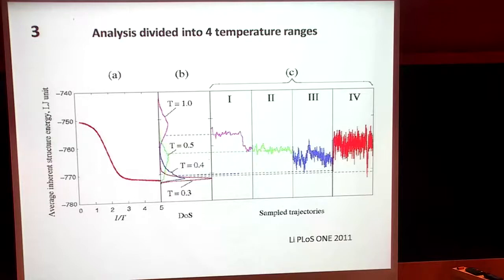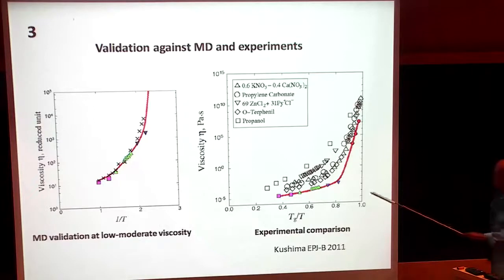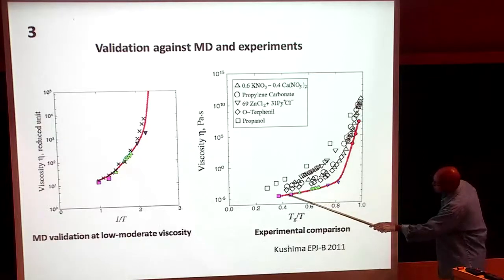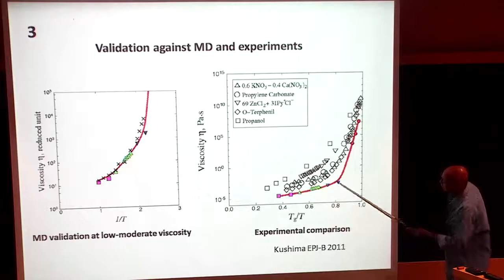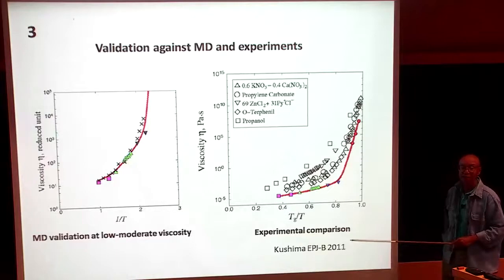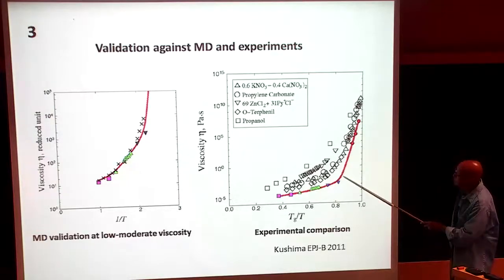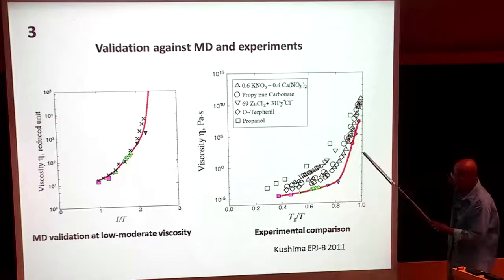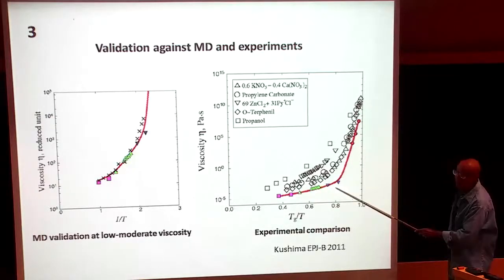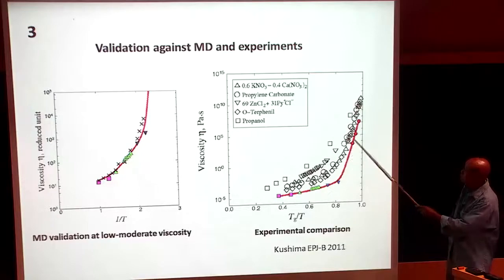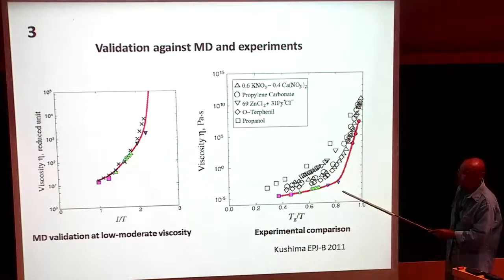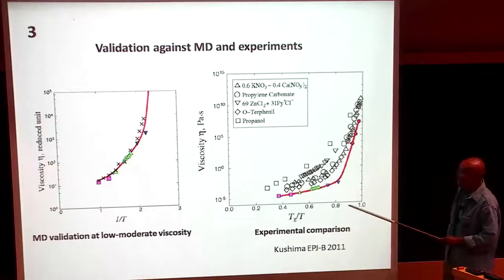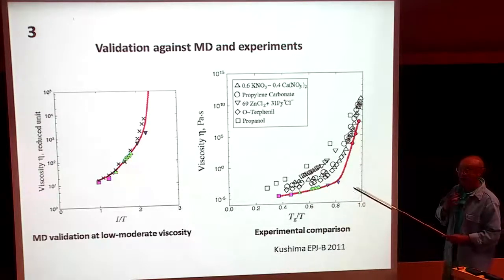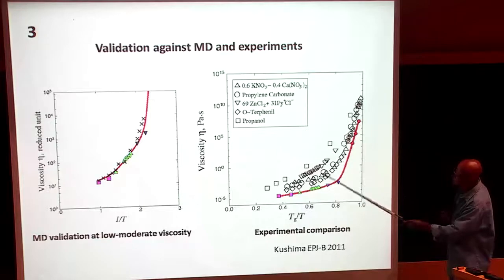But let me show you what we got. Good or bad? These color symbols are the points that we got from the 4 temperature ranges. And this red curve is actually a curve drawn through these points. So the real calculation comes from these points. The red curve is not an experimental curve. The whole thing is to hope that we capture this sort of trend.